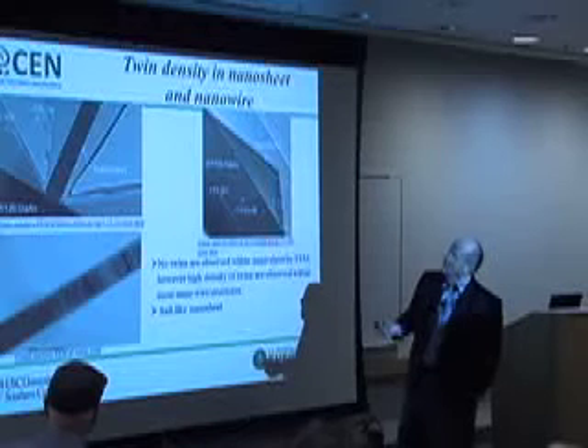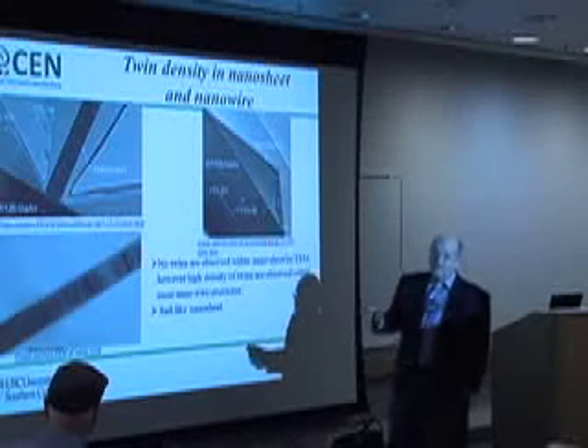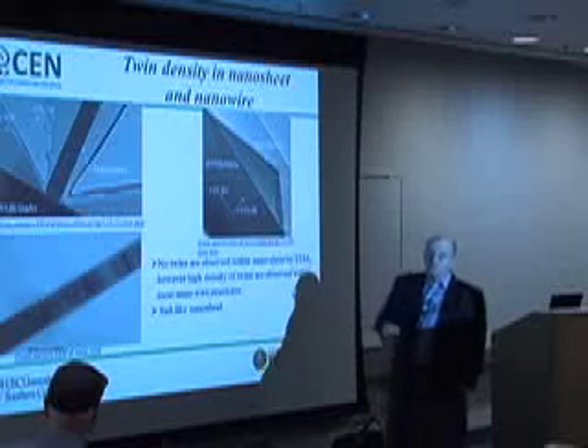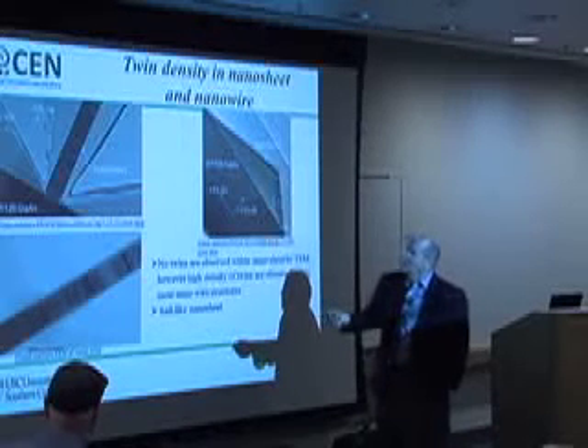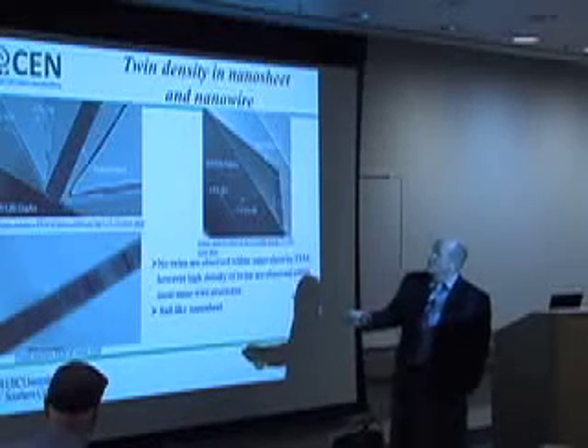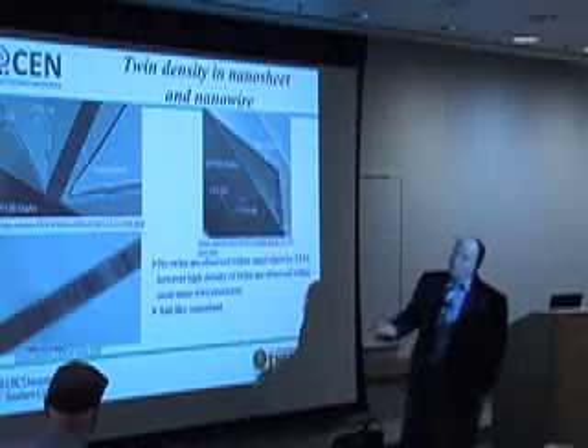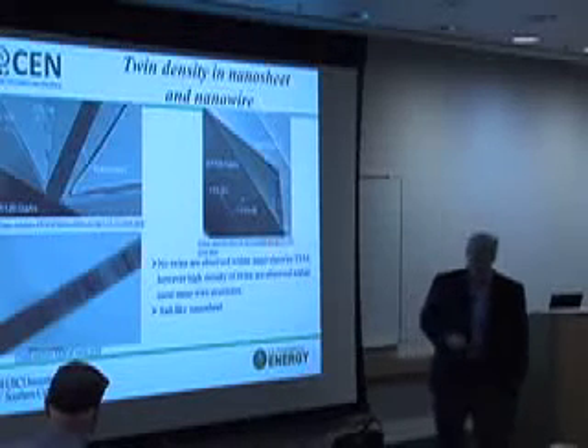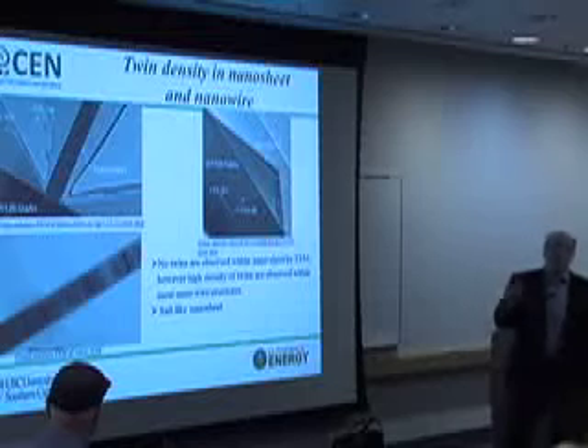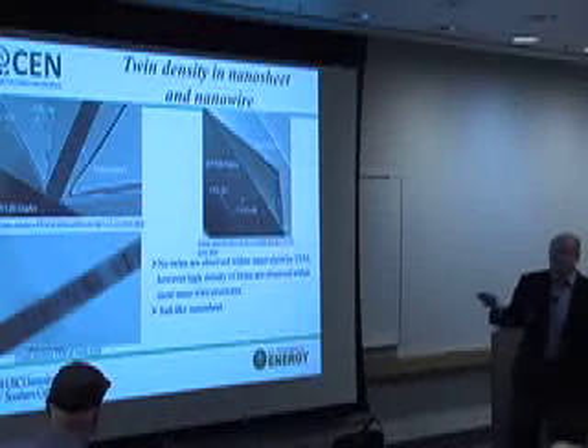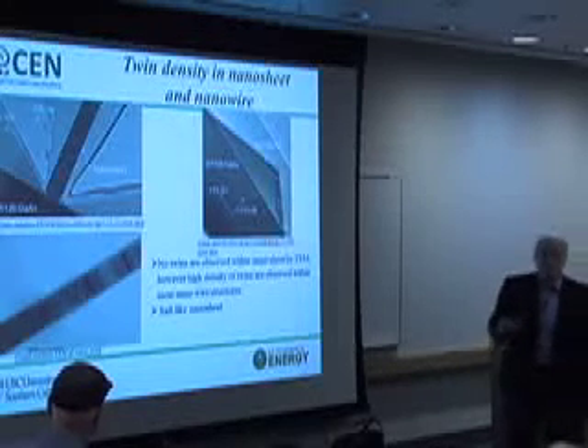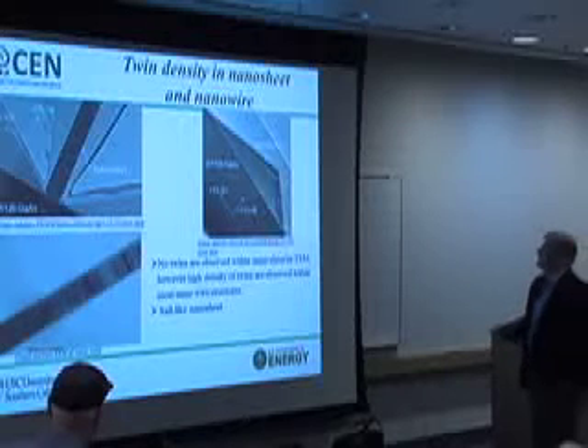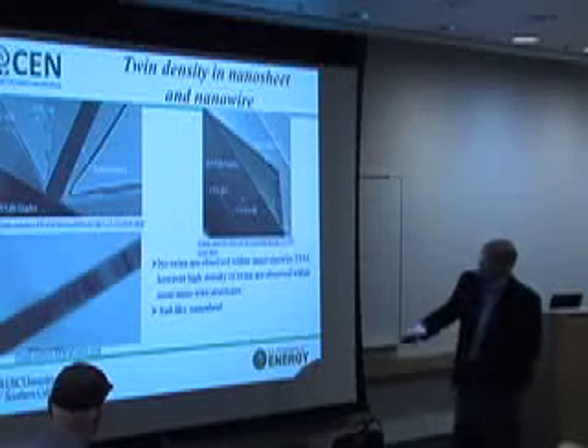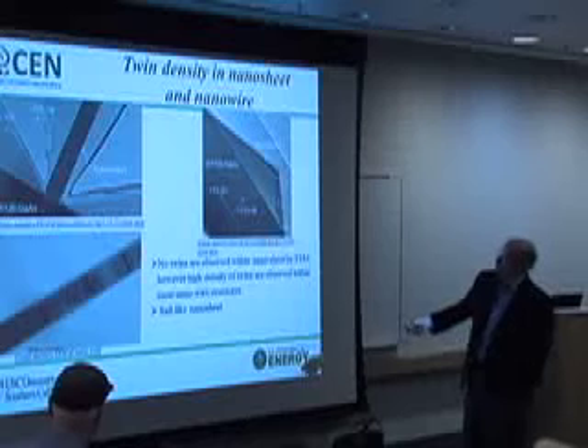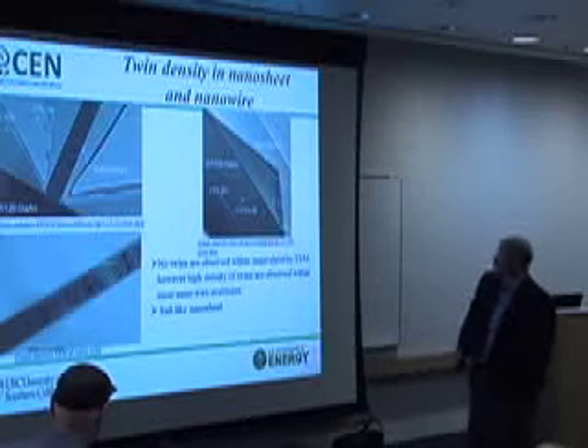And incidentally, when you grow them on silicon or when you grow them on gallium phosphide, all of the misfit dislocations form right here, and there are none that propagate into the structure. So it has some potential implications for integration on silicon or other lattice mismatch materials as well. Now, incidentally, this is a nanowire by comparison, looking at these two cross-sections.